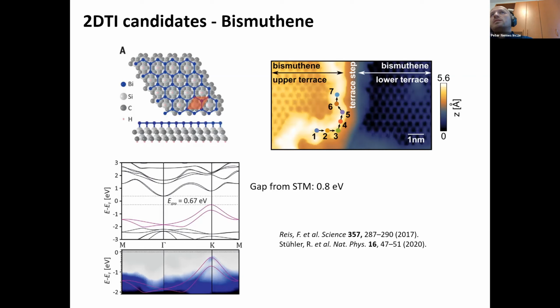In these two cases, and most others that I have not mentioned here, so for stanene and for this bismuthene, the crystal structure of these materials is intrinsically linked to that of the surface. So these materials do not exist without the surface on top of which they are grown, or it would be very hard to remove them. So this is a no-go area from an experimental point of view. They are 2D materials, but they don't have the flexibility of self-supported 2D materials. So we should look to van der Waals 2D materials.